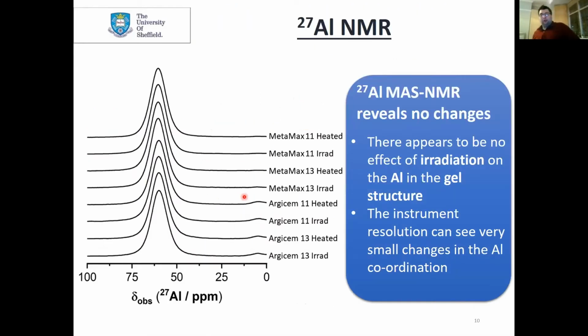So let's go down to an even smaller scale and start looking at the nanoscale. I've done this by magic angle spinning NMR for the aluminium-27 nucleus, which is a key part of the gel structure within a geopolymer system. These samples take around an hour to run each. Silicon is another major component, but running that is a 6-hour scan, and to be honest it costs a lot of money to run the machine that long. It also doesn't show us much more data—it shows different data, but chemical stability should be shown from the aluminium data.